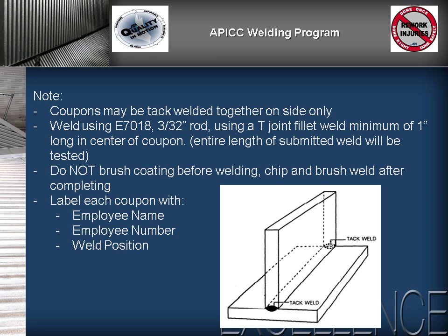You will then place a fillet weld on one side of the joint using E7018 3/32 inch rod. The weld must be a minimum of 1 inch long, and note that the entire length of the weld is subject to a visual and destructive test.